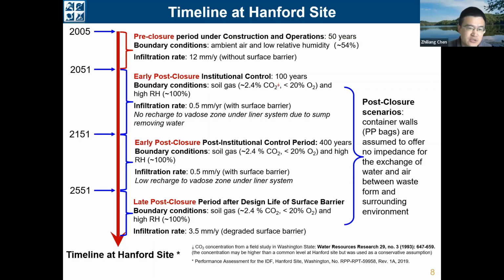And under the post-closure scenario, the aging condition will be changed from the ambient air to the soil gas with higher concentration of CO2 and also higher relative humidity of around 100%. And specifically for the early post-closure scenario, the infiltration rate is only 0.5 millimeters per year because at this stage, there is a functional cover at the top of the facility to prevent the infiltration. But for the late post-closure scenario, the infiltration rate will be increased from 0.5 to 3.5 millimeters per year because of the degradation of the cover.